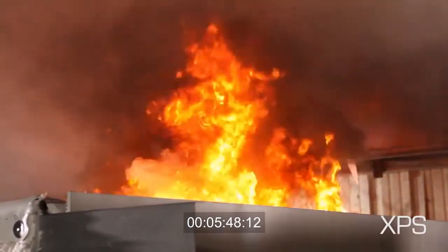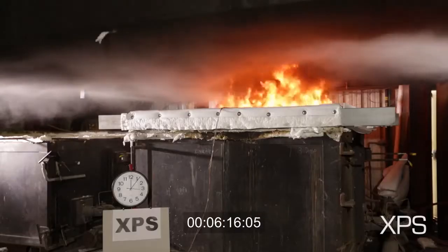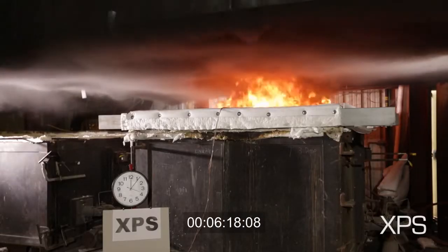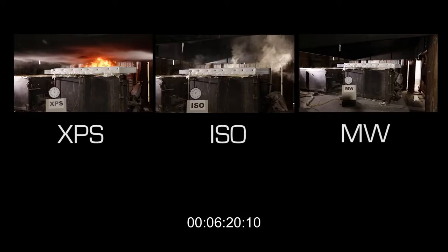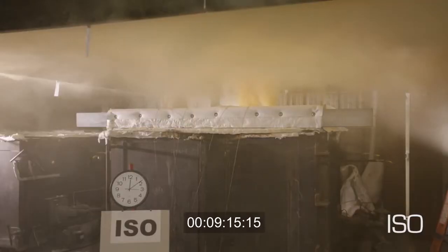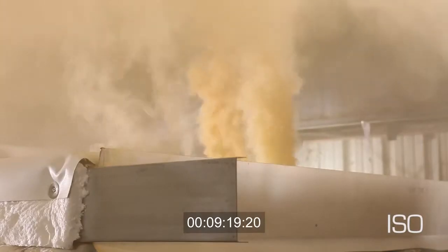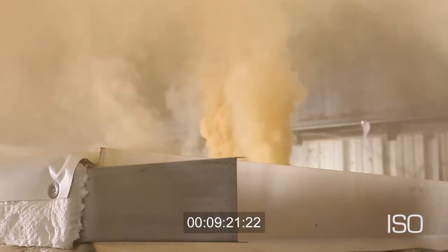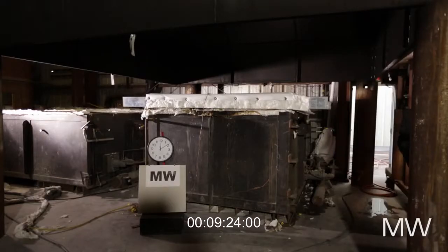Now immediately after the initial flame through we see that the fire grows very rapidly, as does a large quantity of smoke being emitted from the specimen. The test is extinguished shortly thereafter. At 9 minutes, the polyisocyanurate material begins to smoke heavily, and we also see the emission of yellow, heavy smoke. At that stage, the mineral wool specimen is still intact at that same time.